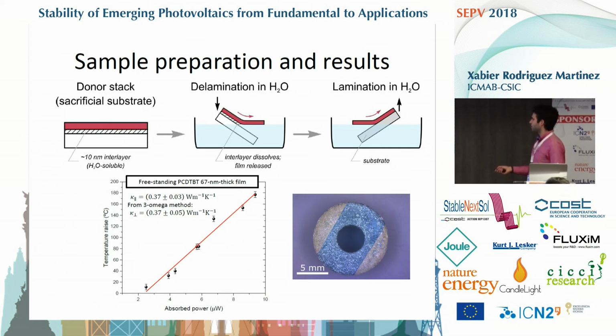And we can do this basically in freestanding films that we prepare by this process here, in which we basically deposit a water-soluble layer. Then we put our polymer of interest or material, we delaminate it in water, and then we laminate it again in basically a metallic washer, so that here in the middle the film is completely freestanding, and we can do our thermometry experiment. And this way we can get the thermal conductivity in plane of this freestanding material.